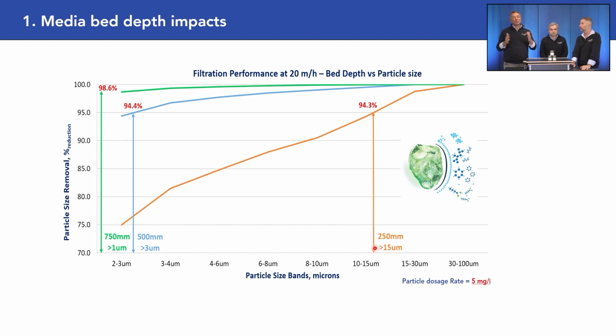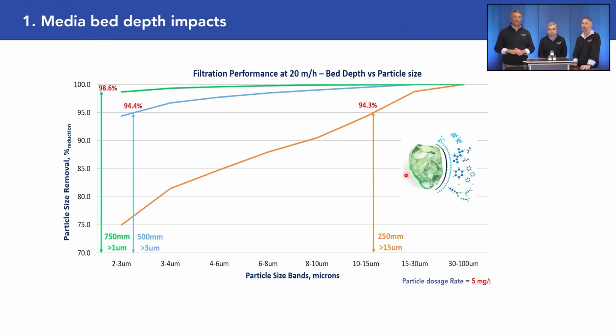And this is why we always recommend to stay, if possible, in a filter bed of roughly 500 millimeter of the main media, so grade 1 or grade NG. To be fair, if you slow down the filtration velocities, especially in gravity filters where we have 5, 6, 7, 8 meters, then this difference becomes much less. But the higher the filter bed, the better the filtration, particularly of the fine particles, which we're looking at.